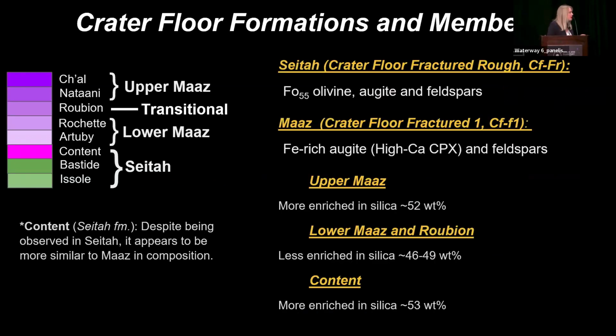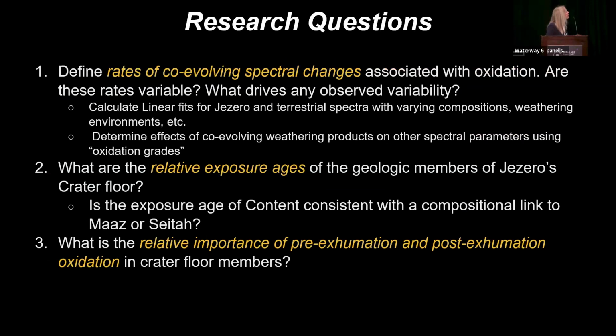So the composition of these units varies significantly. Seitah is broadly composed of Fo55 olivine, augite, and feldspars, whereas Maz is just the iron-rich augites and feldspars. And upper Maz is very enriched in silica content at about 52% on average. Lower Maz and Roubion are slightly less enriched at about 46 to 49% on average of silica. And Content is more similar to upper Maz in its silica content at about 53% on average.